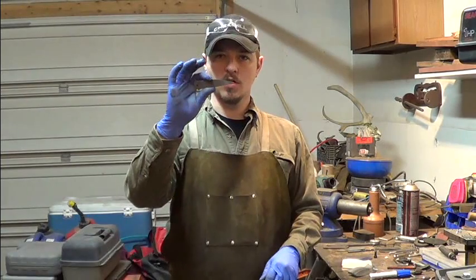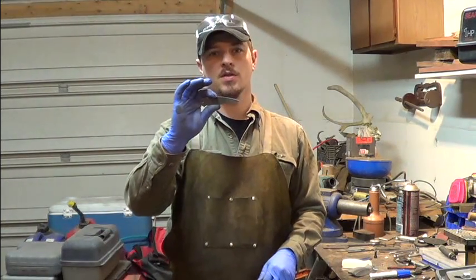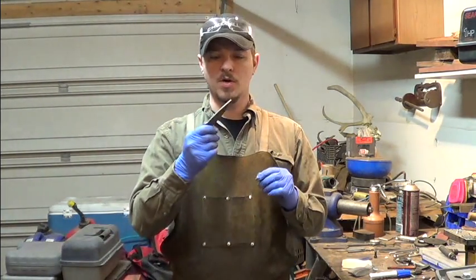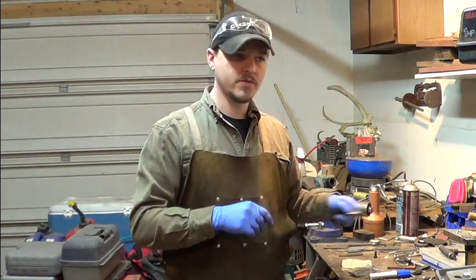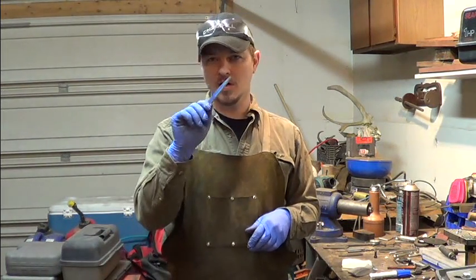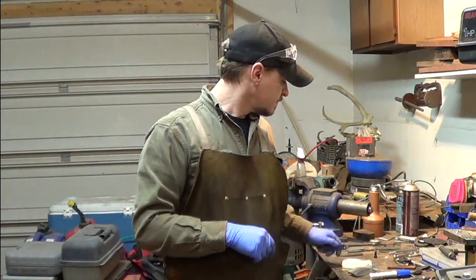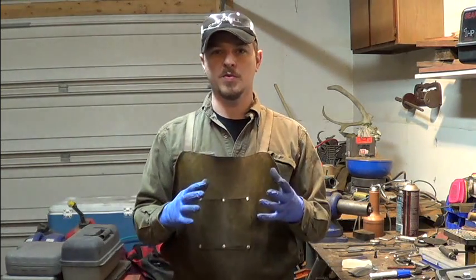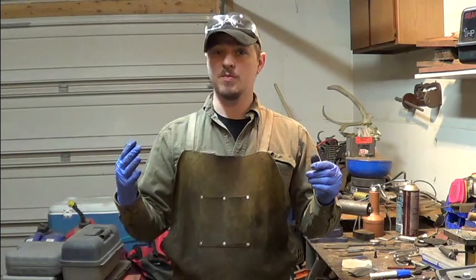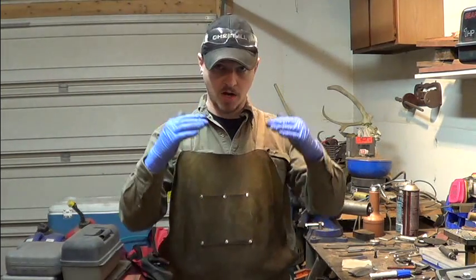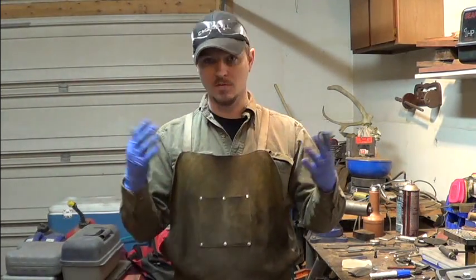And then these are going to go back in the oven for another 2 hours, and after that they'll be at about a 60 Rockwell, and then after these get out of the oven, I'll be about a 58, 59 Rockwell. And that's the difference between the steels. It might be the same temperature in the oven, but it brings the hardness down to different levels depending on the alloys in the steel.